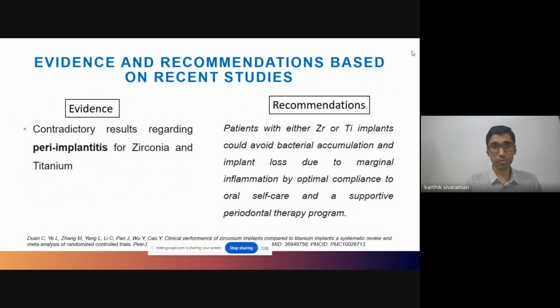Then, as we discussed before, there were contradictory results regarding peri-implantitis for zirconia and titanium. So the recommendations of the authors were that the patients need to have good oral compliance and a supportive periodontal therapy program to avoid bacterial accumulation and implant loss, regardless of the fact that they were treated with titanium or zirconium.